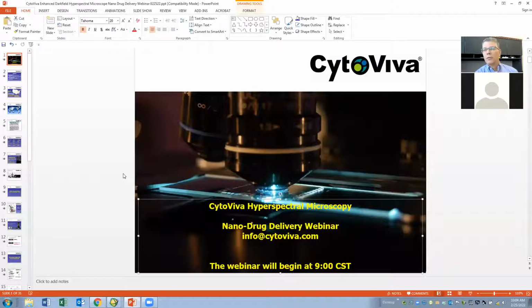300 nanometer gold particles aggregating are going to produce a different spectrum and are going to look different than a single. And we've also done a lot of work in the dimer world where 40 nanometer or 60 nanometer gold nanoparticles are purposely placed nanometers apart. And that creates an amplified effect. Dr. Naomi Halas's lab out of Rice University has done a lot of work with this, where they look at specific dimers, and hers were silica gold shells, but it doesn't matter. You're going to get really specific optical spectrum based on how close those particles are apart from each other. There's an amplification effect that takes place there.